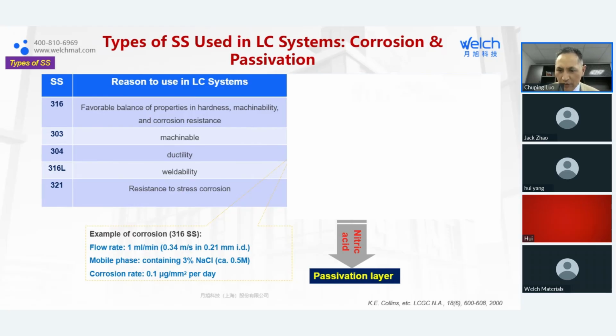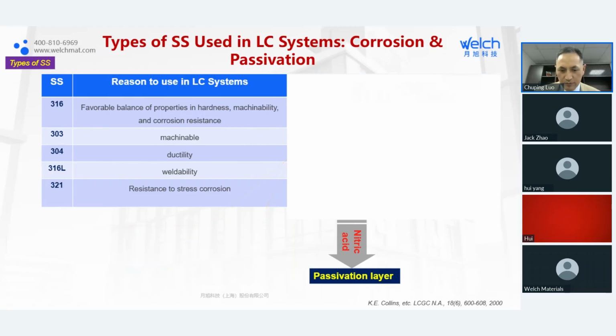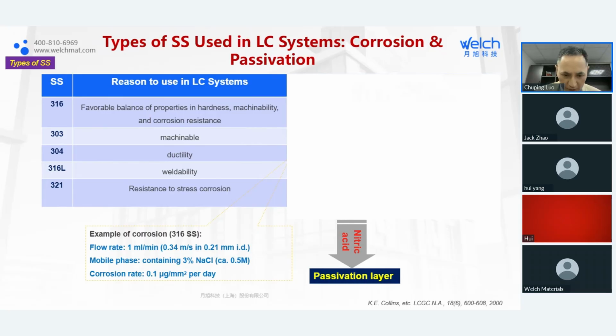Another study says that even if you run the system faster, the corrosion happens faster. Here's an example using 316 stainless steel, where the flow rate is 1 ml per minute but the ID is very small, so of course this is a pretty fast flow. Another thing I need to point out is the mobile phase, which is sodium chloride. That's something very dangerous to your system. It says 0.1 microgram per square millimeter per day. That sounds like not much, but if you calculate for a month or a year, that's a significant amount.